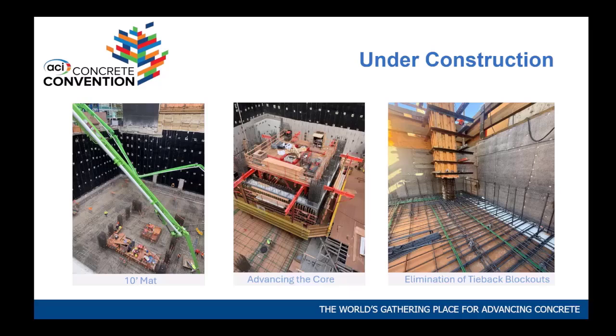So that's one. Two is we cover it so we keep the heat differential the same between the center and the top of the mat for a few days till things come down. We'll look at the temperature gauges for that. The other cool thing is it's a pencil tower in the downtown, so it's 120 feet by 100 plus feet, 110 feet. So you want to go fast, and the basement wall creates a trouble because if you have to pour the basement wall, pour the slab, pour the core, you'll be stuck in that hole 6 levels below grade